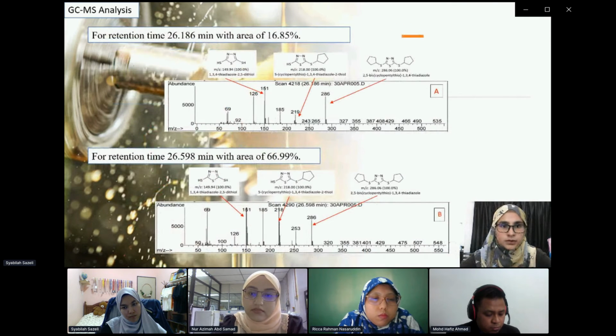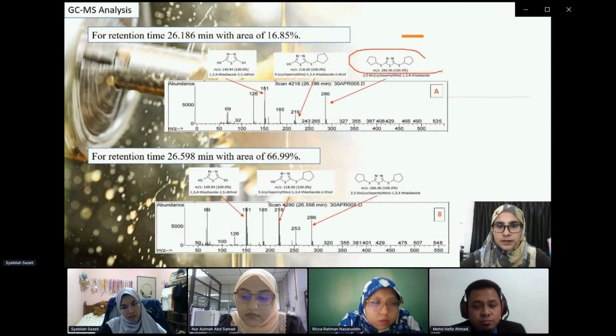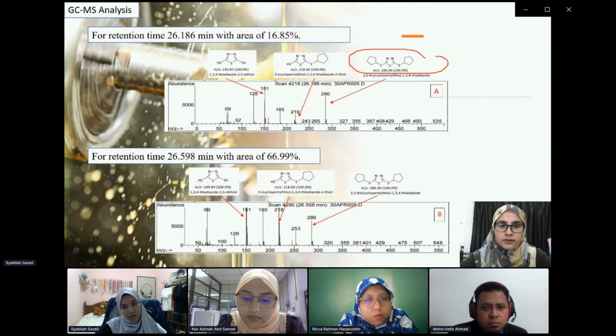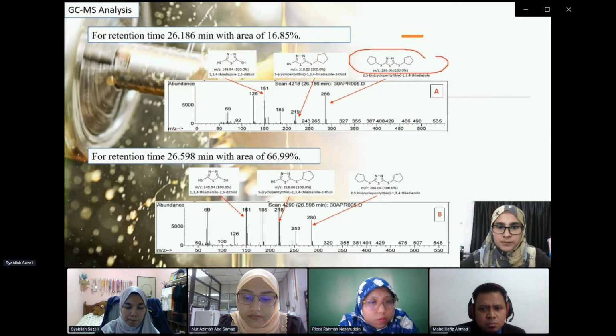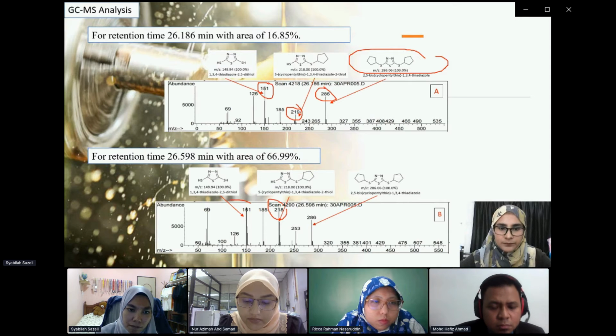So this slide shows the mass spectrum for this alkylated compound at retention time of 26.186 minutes with area of 16.85% and 26.598 minutes with area of 66.99%. So from both spectra, it shows two rotamers of this alkylated thiadiazole with total mass above 83% and no reactant is detected. Also, the same fragments of m/z 286 are observed at 219 and 218 and also 151.